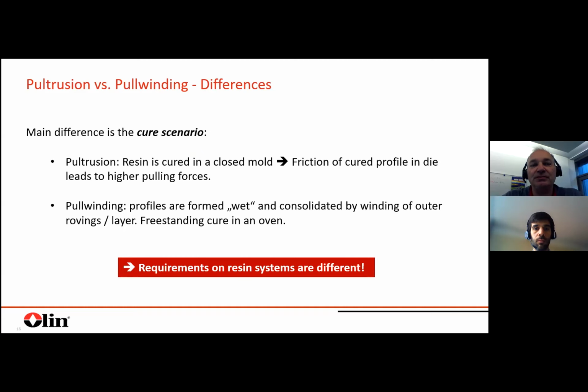So in pultrusion, where you have a well-defined shape, you have a closed mold where you gelate and cure the resin. Which means you created in this closed mold a kind of friction, which leads to higher pulling forces. And there you have specific requirements on the resin, which is linked to this. I will come to this in a minute.